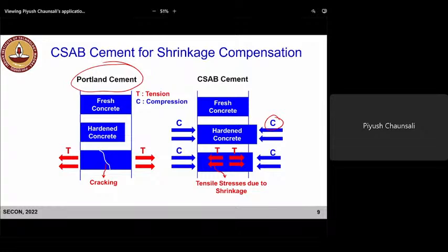So idea is, again, it's not like this concrete is not going to shrink overall, but the compression is going to take care of this tension. So overall, we can compensate for shrinkage through this expansion. So it's like compression will take care of part of the tension or tensile stresses due to shrinkage. So CSAB cement can also be used for shrinkage compensation.